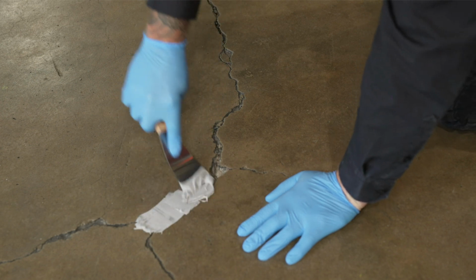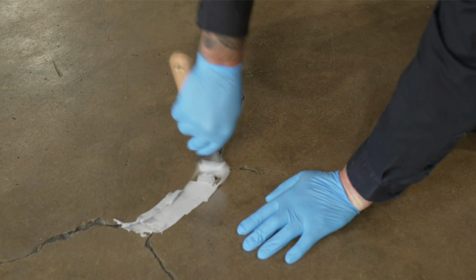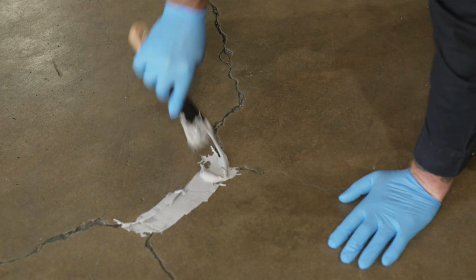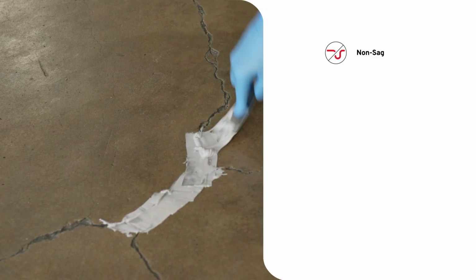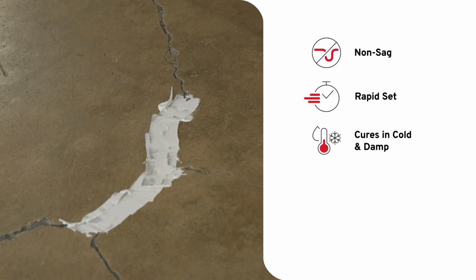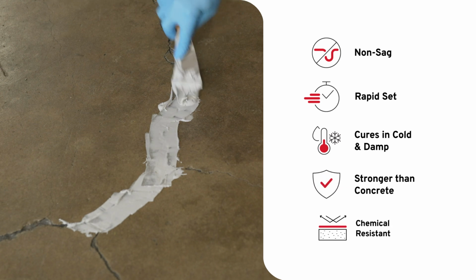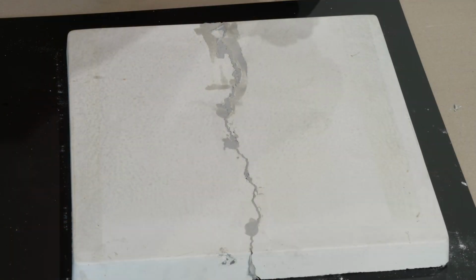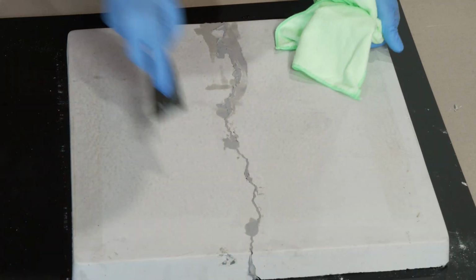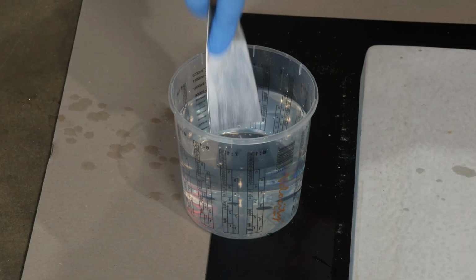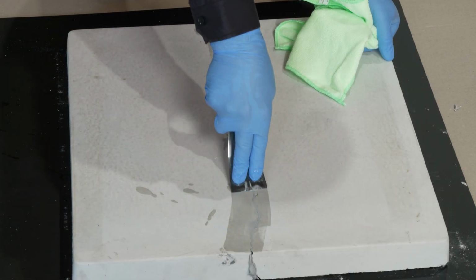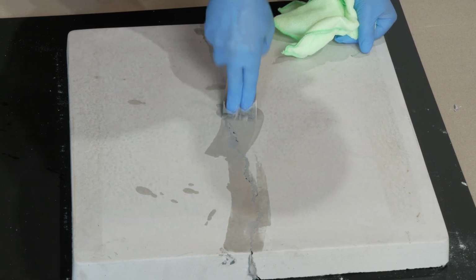Applying Megapoxy P1 to cracks and holes is easy and fast. And because it doesn't sag, P1 is ideal for overhead or vertical surfaces. Uncured P1 can be cleaned with Megapoxy thinners. It's rapid setting and will cure even in cold or damp conditions, stronger than concrete with good chemical resistance. A smooth polished finish can be achieved by wetting a clean spatula and gliding it over the surface towards the end. However, never mix water into the combined part A and part B.